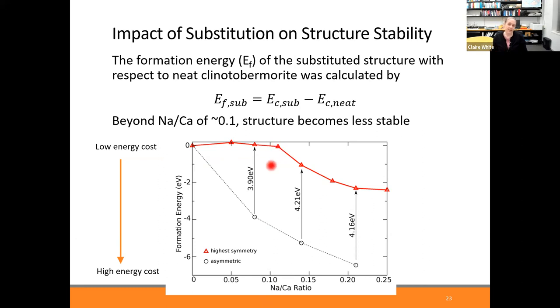And this is interesting. This is giving an indication that you can have some sodium present, but there's a point where you get too much sodium. And so what is likely going to be important from an experimental viewpoint, if you make these concretes, is you don't want to dose the system with too much sodium, because it could be causing the gel to be less stable, which could make it more prone to change over time.